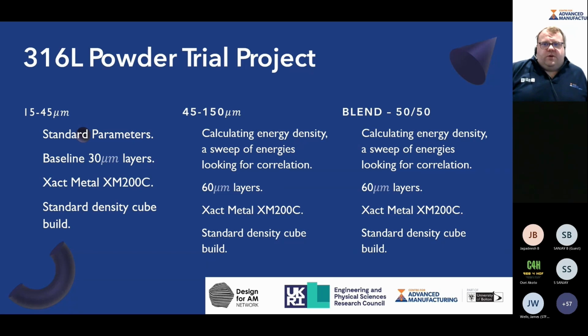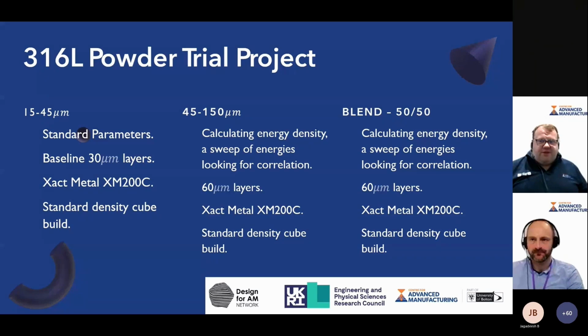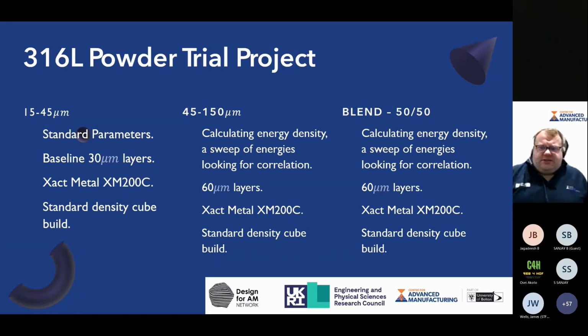We then also looked at a large and oversized cut, a 45 to 150 micron cut. For the quick experiment we doubled the layer height, and then we calculated energy density to create a sweep of different opportunities. So three powders. The 15 to 45, I think I explained that. The other two were an energy density sweep, and we're just looking for some correlation between energy density and mechanical performance, with 60 micron layers. What we tried to do was create a 50-50 blend, so 50% of the 15 to 45 plus 50% of the 45 to 150. Same builds in all cases, and it was a first dip check.